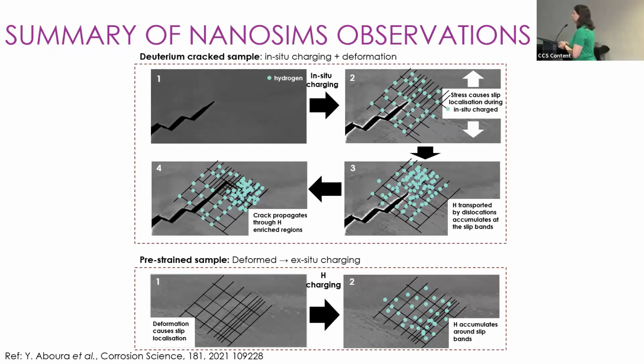If we just have the pre-strained sample, we do get hydrogen accumulating around dislocation slip bands, but not to the same extent that we saw with the sample that was being cracked. And obviously hydrogen is causing a brittle failure in this case.